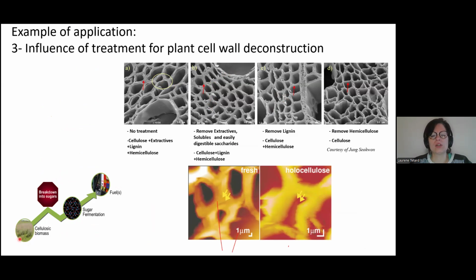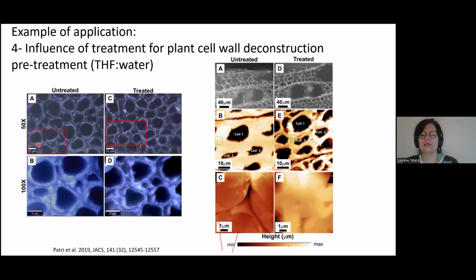That's because I was part of a project where we were trying to understand biomass recalcitrance for biofuel production. One of the studies we did here was to look at a cross-section with optical imaging, and then to take this small piece of material and do pre-treatment in some solvent. Here it was THF in water. Take the section out of the reactor and find exactly the same region on the tissue and compare the property of the cells before and after. Those were the cells numbered cell 1, 2, 3, and the same cells after treatment. And then we see that at the cell corner here with the 3 cells around it, this region is completely modified. Its morphology is changed after the treatment.